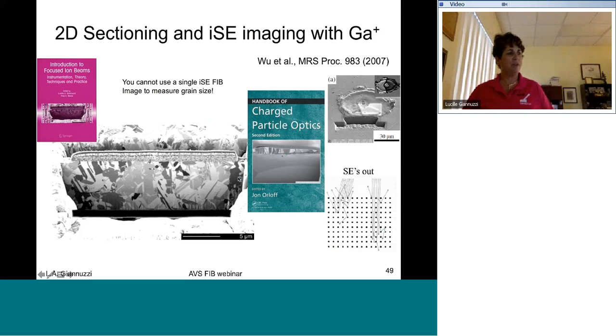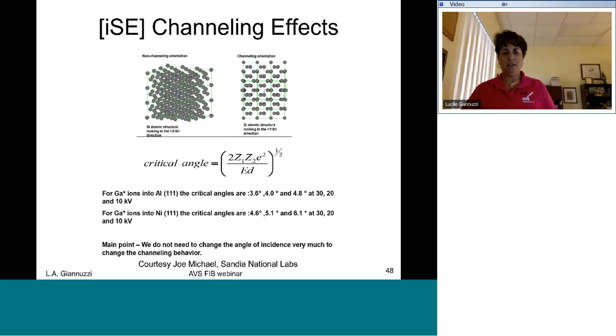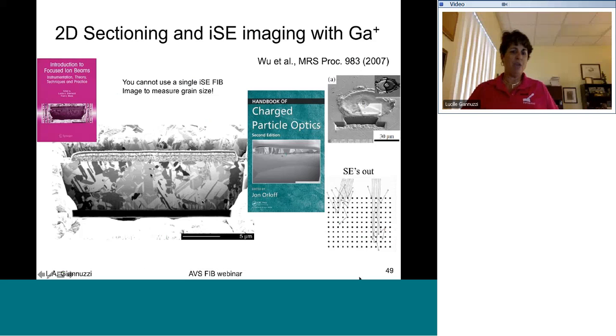What this also means, however, is that you have to be really careful on how you interpret this, because, let me go back again, the critical channeling angles are small, like 3, 4, 5, 6 degrees, and our definition of a grain boundary is sometimes 10 or 15 degrees or larger. What this means is that we can see differences in contrast that may or may not be due to differences in grain boundaries. They may be just differences due to strain.